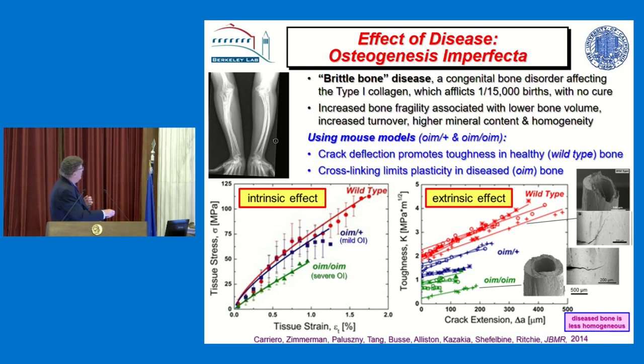Why? Well, because there's far more mineral in the bone. Instead of all the mineral being in the boundaries of the osteons or the regions, it's spread throughout the bone. So there's no particular need for that crack to deflect. And that's seen in a lot of different bone conditions. The medical reasons are different, of course, but the loss of toughness is generally due to cross-linking, which limits the intrinsic deformation of the collagen, and the fact that you don't see as much deflection of cracks or formation of bridges in the bone, which is either diseased or aged.